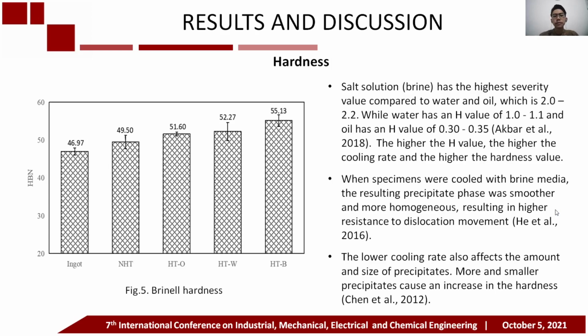And then we go to the discussion about hardness. The results of hardness are shown in figure 5. Salt solution or brine has the highest severity value compared to water and oil, which is 2.0 to 2.2, while water has an H value of 1.0 to 1.1, and oil has an H value of 0.30 to 0.35. The higher the H value, the higher the cooling rate and the higher the hardness value. When specimens were cooled with brine, the resulting precipitate phase was smoother and more homogeneous, resulting in higher resistance to dislocation movement. The lower cooling rate also affects the amount and size of precipitates. More and smaller precipitates cause an increase in the hardness.